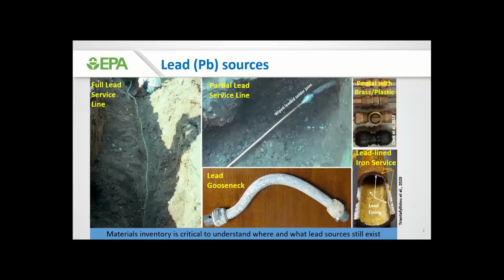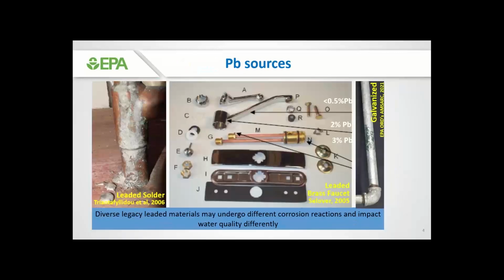It is important to know where and what lead sources still exist. So materials inventory is certainly critical to understand all of these sources. And of course, aside from the pure lead pipes or pure lead linings, we may also have still legacy lead alloys around, such as leaded solder on the photo on the left here. You can see a very poorly made leaded solder joint kind of seeping on the outside of the copper pipe, but it actually seeped on the inside, came into contact with drinking water, and contaminated drinking water at the tap in this specific location of a lead poisoned child.